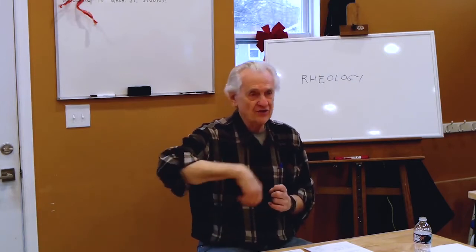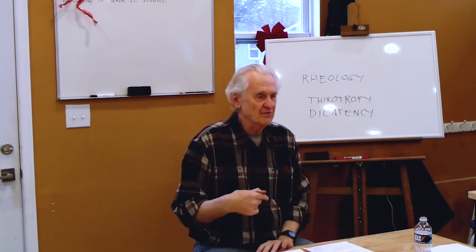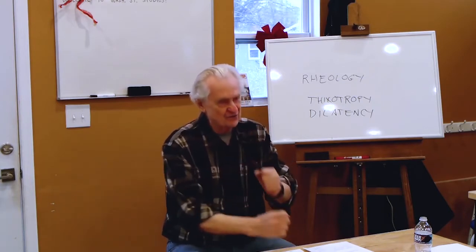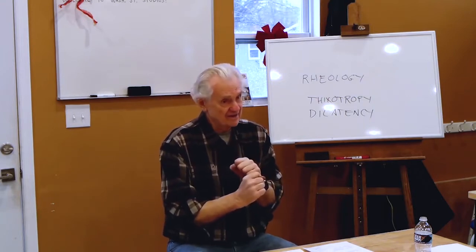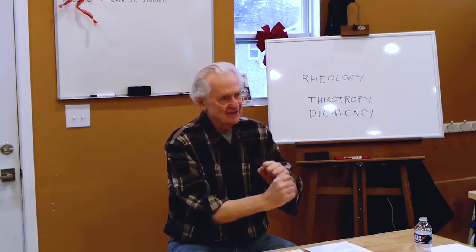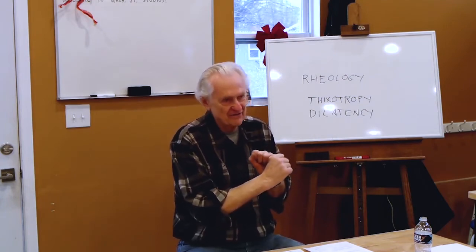Dilatancy is the opposite. The harder you try to stir it, the more it resists, and it gets stiffer. Not to get too off track here, but a good example of dilatancy is the stuff that settles out to the bottom of a glaze, the sludge. It's almost impossible to get a stick into it. That stuff that has settled out to the bottom is dilatant. The harder and faster you poke at it, the more it resists. You have to slow your whole body down and stir it slowly, and you can get it to move. If you do it fast, you're never going to get it to move.